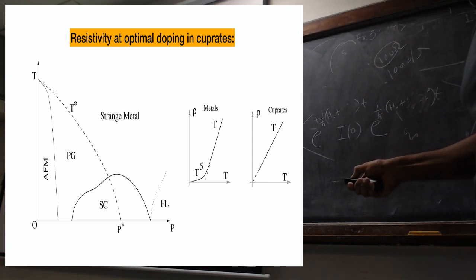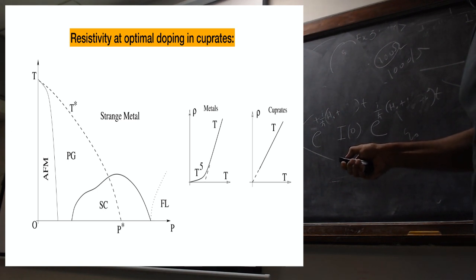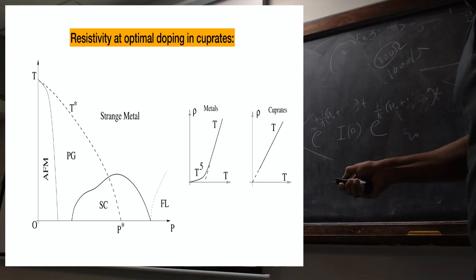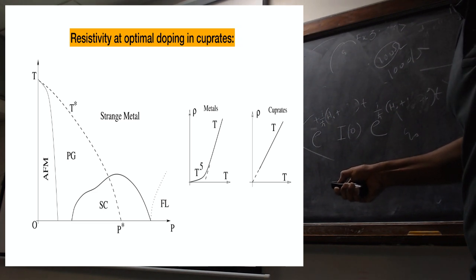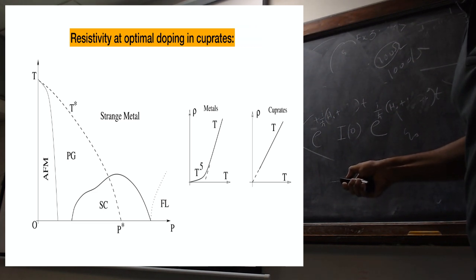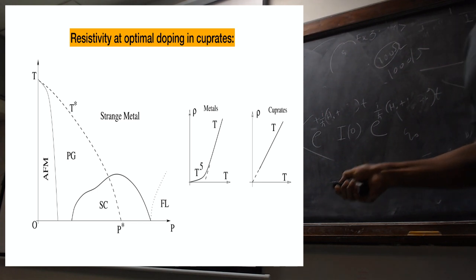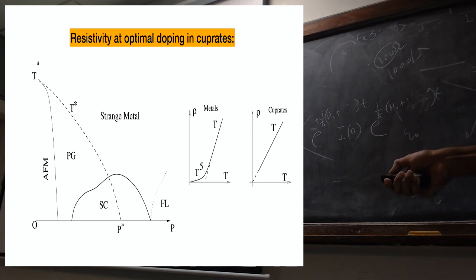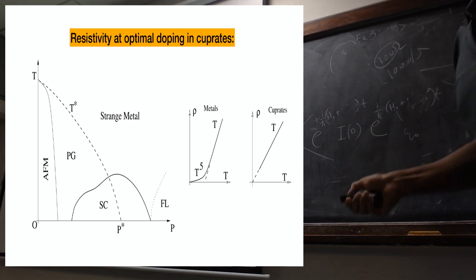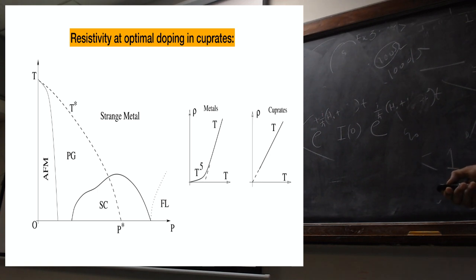This is a cuprate. This is a typical metal. What happens if you take a typical metal? At room temperature it is T linear. At low temperature it starts to bend. People have done experiments going down to millikelvin. They see complete T linear behavior. Some fundamental scaling law is going on. People have coined the word Planckian dissipation. Okay, so how far does the T linear go? It goes from millikelvin up to 800 Kelvin, really very hot temperatures, all T linear.